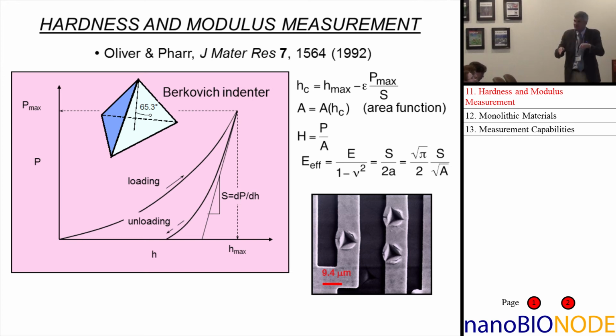If you know the area function, as we call it, the geometry of the indenter, then we can get the area. If you know the contact area, then you know the hardness, because the hardness is the force divided by the contact area. And then through this fundamental equation of nanoindentation, then you can get the effective elastic modulus. The effective elastic modulus is Young's modulus divided by 1 minus Poisson's ratio squared.